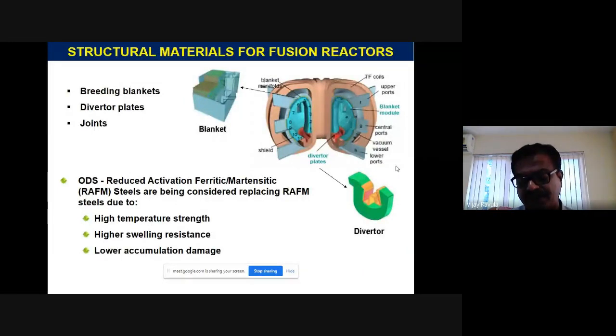So that's all in the fast breeder reactors. Coming back to the fusion reactors, India is a partner in the International Union on the development of fusion reactors, where we have blanket plates and divertor plates, which also get radiation exposure and high temperatures, so the materials have to be developed to withstand these. So you need high temperature strength, high swelling resistance, and lower accumulation damage. The material should not become radioactive, but anyhow it will, so the activation life should be as short as possible. That's why reduced activation ferritic martensitic steels are recommended for this activity.